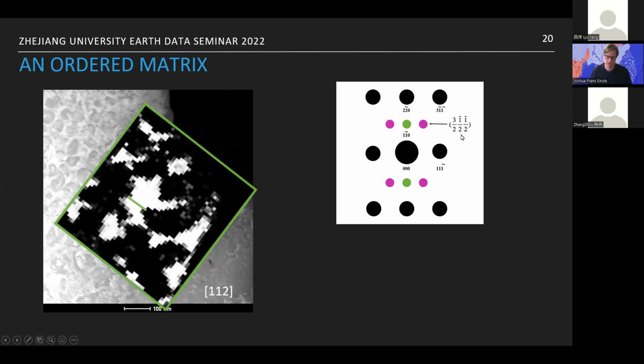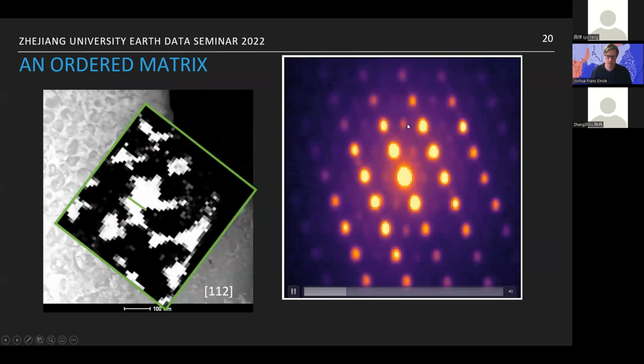Let me explain again. This reflection here is a forbidden reflection. It's not expected in a cubic material, so the fact that we see it at all and have any intensity at this point is unusual. If we watch this movie, we can see that this forbidden reflection is shifting its position as we scan back and forth. Let me loop that again. The whole thing is that this superlattice, which is due to chemical ordering in the matrix, is rotating in space.